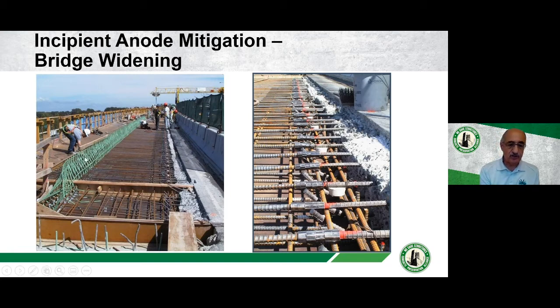So in this case, there was a bridge being expanded, widened. You have the original road on this side, and you're adding a lane. In this case, you're connecting the steel reinforcement to the old steel reinforcement, and you have old concrete, and you're going to place new concrete, of course, on the new construction. That is a susceptible area because it's likely to be, even if it's only low contamination, the pH will be lower. So immediately when you connect the two together, this is going to take the form of the anode, and this new patch is going to drive the anode and drive the corrosion. So installing anodes along the edge of this joint would stop this incipient anode formation.